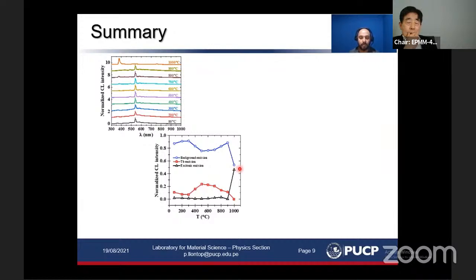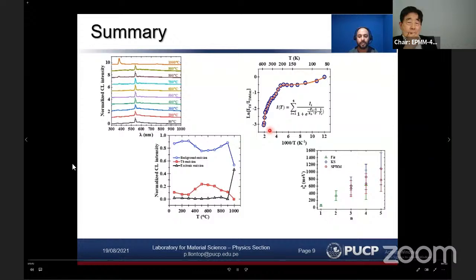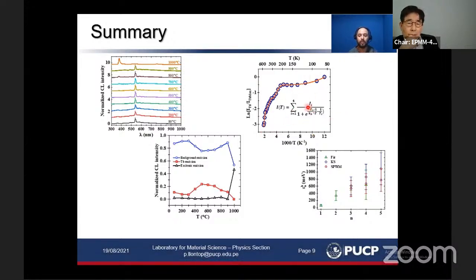And we took a sample with a slightly higher terbium concentration, and we found, by means of temperature-dependent PL experiments, that there could be 4 activation energies, and we relate these activation energies as binding energies of excitons that are bound to the terbium clusters. So we took 2 models for this interpretation and found the corresponding binding energies, and we found that for the cluster with 3 and 4 ions, the experimentally obtained binding energies and those calculated binding energies with both models are in well agreement.